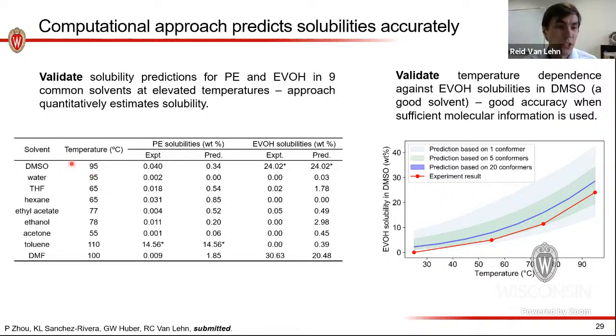So here, for example, are just 9 common solvents at various temperatures where we can measure the solubilities of polyethylene or ethylene vinyl alcohol. This is a common component of plastic packaging. On the right-hand column, I'm showing our predictions from simulations. On the left hand, I'm showing experimental measurements. So we see pretty good agreement, and especially in terms of figuring out which of the solvents dissolve these to a very high rate and which dissolve them to a very low rate. In other words, which might be appropriate for selective dissolution and which might be appropriate as an anti-solvent.